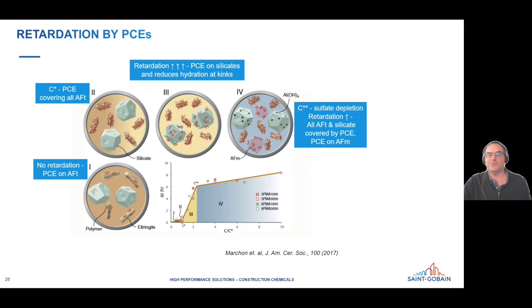So now you see a much steeper relationship here. And then when those are saturated, it goes on and adsorbs onto something else, and you get a shallower behavior here. But overall, you can see this plot going up 6 or 8 hours. You don't want 6 or 8 hours of set time retardation normally. So you either need to use a lower dose, or you can add in another component, an accelerator, to compensate for that effect.